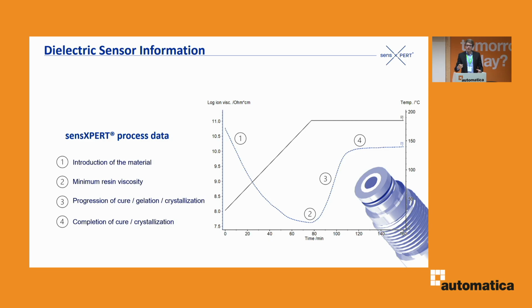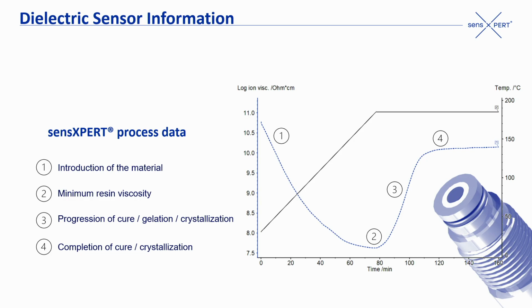What this means is the material is starting to react. There's a chemical reaction occurring, and the material is hardening, right? It's curing. And this is something that we can detect. And then at some point, this effect is stronger than the decrease in viscosity because of the temperature increase, and that's where the line starts moving up again. And then at some point, our curing reaction is nearing its finish, and that's where we reach that plateau in the end, which is indicated by point number 4 here. So that's when we know, okay, we are almost ready with our curing. At some point, we can define a quality criterion where we say if we have reached this level of cure, or correlating measurement level here, then our part is finished, it's good, and we can demold and have our finished part in good quality.